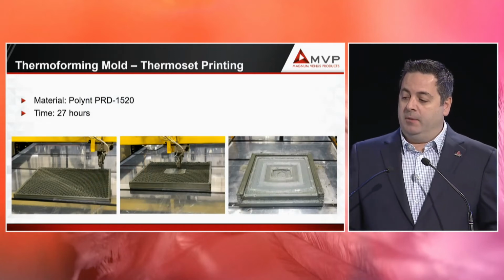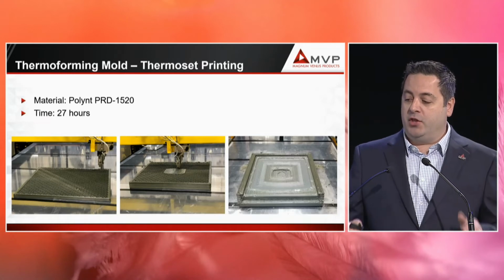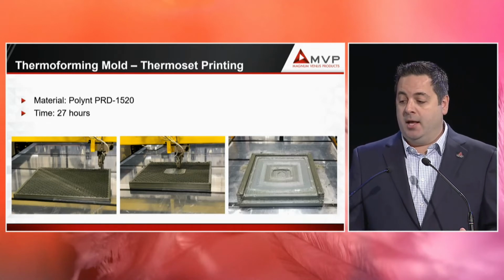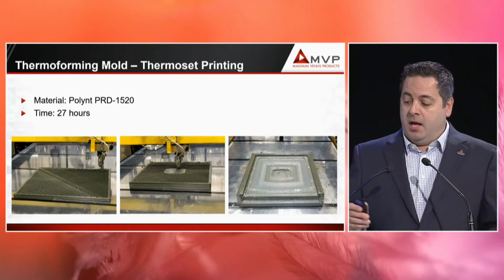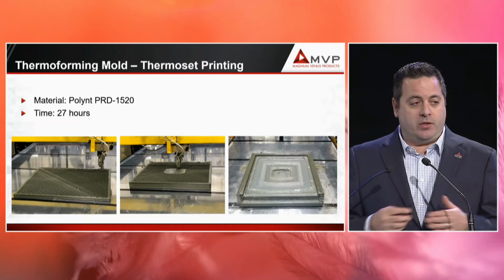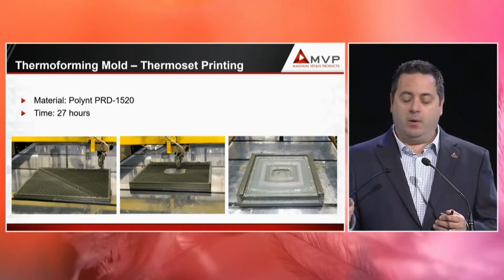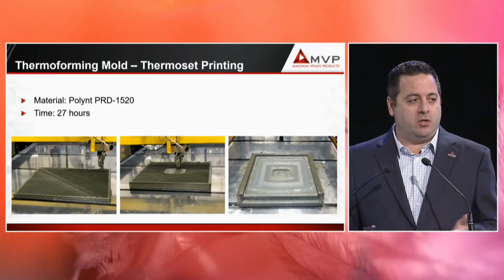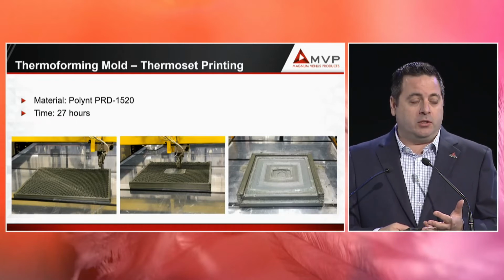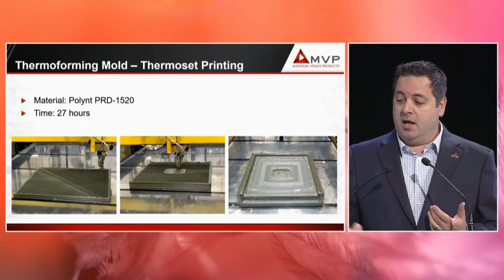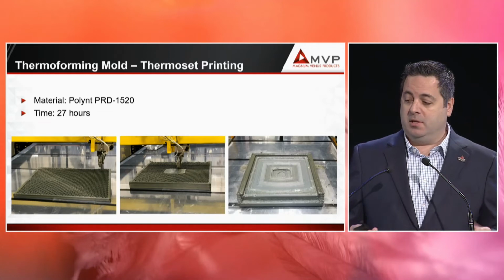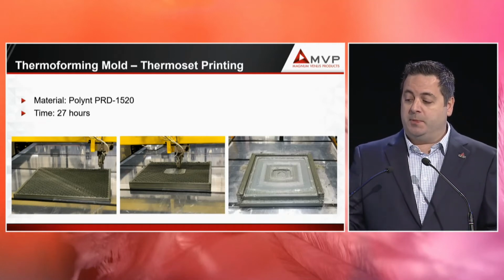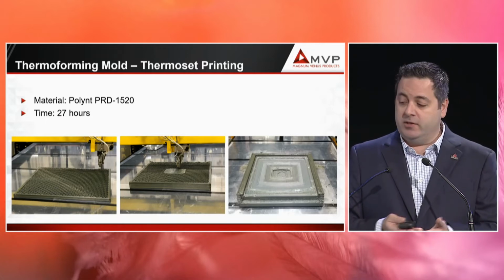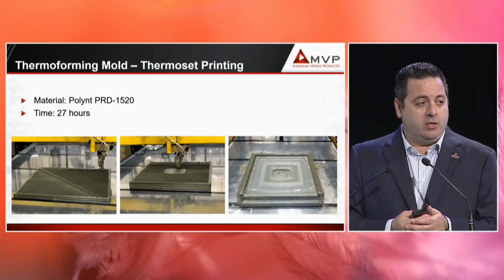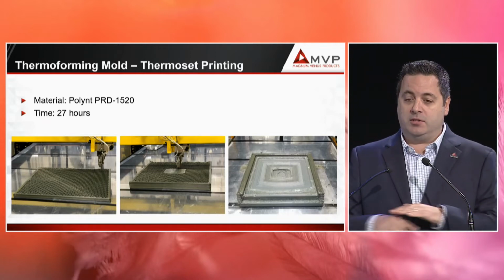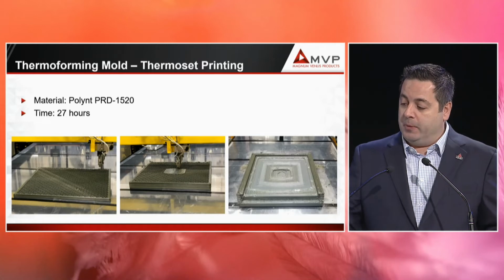So this is a case study. I'm going to kind of break this one down a little bit, of a thermoforming mold for a shower pan. This was also printed with the 1520. You can see in the bottom left, we started this print with a sparse print. So there's a grid work here of about 1-inch crosses, and that was done so that we could lightweight the tool. We were also creating a hollow base for this because it is a thermal forming, so we're going to add a vacuum system to this, as I'll show you in here. So it started sparse. As it started getting closer to the surface of the mold, we started closing those squares until it got to a solid surface, and then you can see the print here in the lower right.